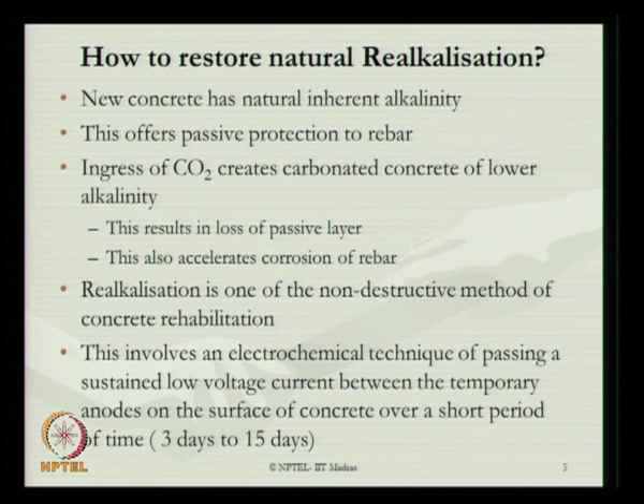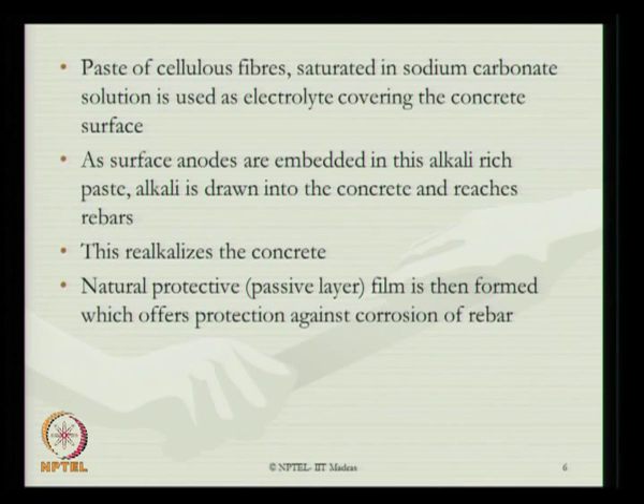This involves an electrochemical technique of passing a sustained low voltage current between temporary anodes on the surface of concrete over a short period of time, and this period can vary anywhere from 3 days to 15 days, and this can be repeated in a number of cycles in a given period of time. A paste of cellulose fibers saturated in sodium carbonate solution is generally used as an electrolyte covering the concrete surface. As surface anodes are embedded in this alkali, alkali is drawn into the concrete and reaches the rebars. This realkalizes the concrete in totality. A natural protective passive layer is then formed, which offers protection against corrosion to the rebar.